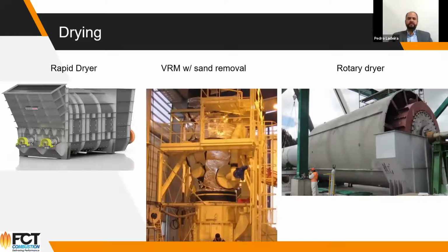Before calcine and flash calcine, you have to dry the material. So you can have different options. We can supply rapid dryers. We can supply a vertical roller mill with the feature of sand extraction. And it's incredible the amount of sand you can have with this inert material. You can remove the sand from the material to be sent to the calciner, which is an advantage from a reaction point of view on the product performance. And we can also apply the rotary dryer as a solution for pre-drying the material.